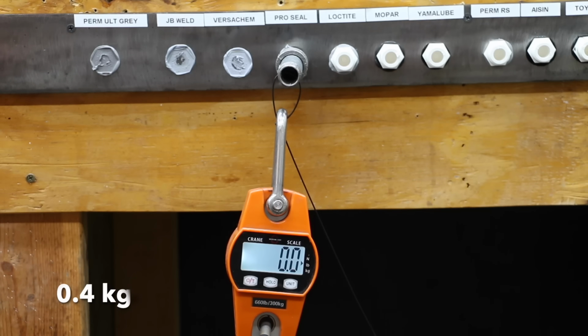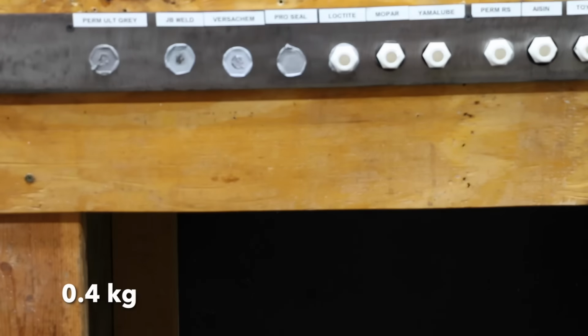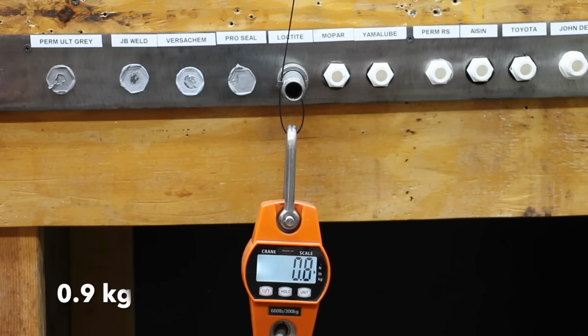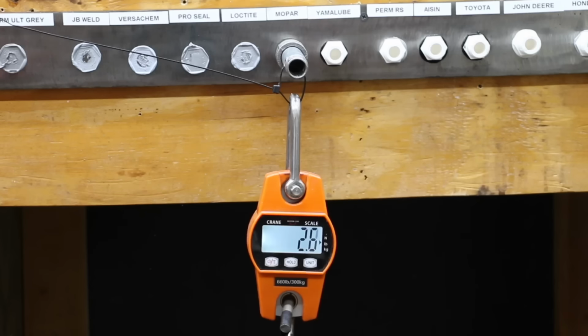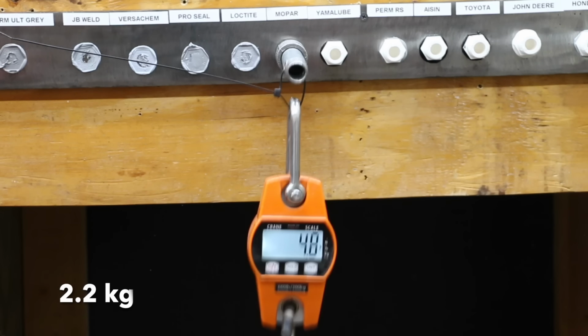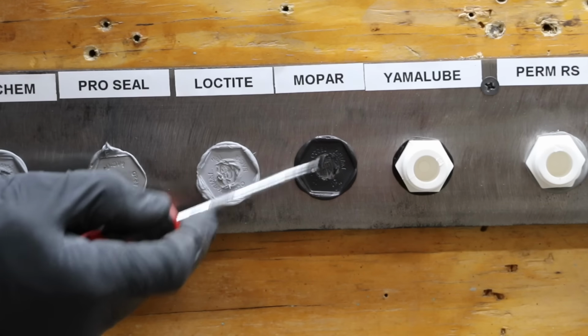Once again, the Pro Seal just did not demonstrate as much adhesive strength as some of the other brands at 0.8 pounds. Just like the Permatex, the Loctite just doesn't seem to offer as much flexibility and quickly released at 2 pounds. And the MOPAR demonstrated very good flexibility and strength, finally letting go slowly at 4.8 pounds.